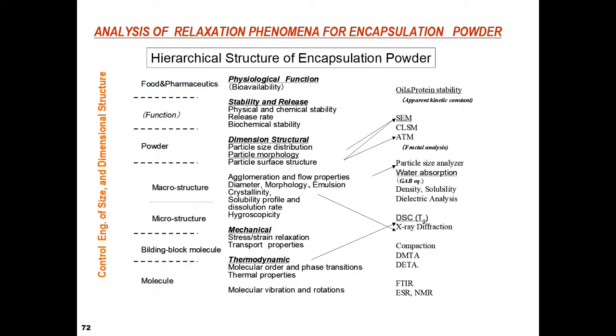So this is some kind of analysis method of the powder, but the easiest method: please prepare a desiccator or a plastic box, and then you can control the humidity with salt, sodium chloride, or another salt, lithium chloride, and then please check the powder state. You only need, recently, a mobile phone is enough. Please take the photo.